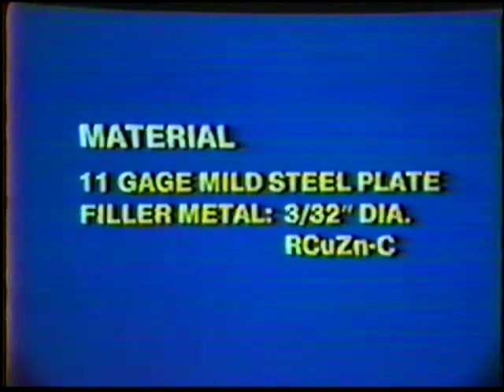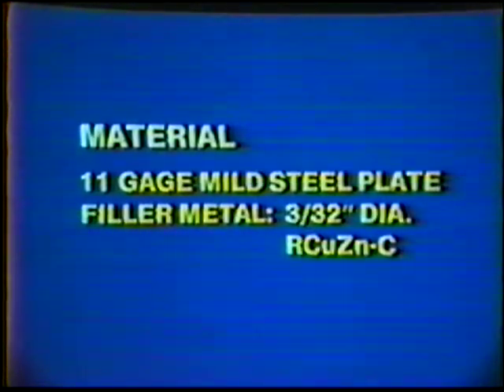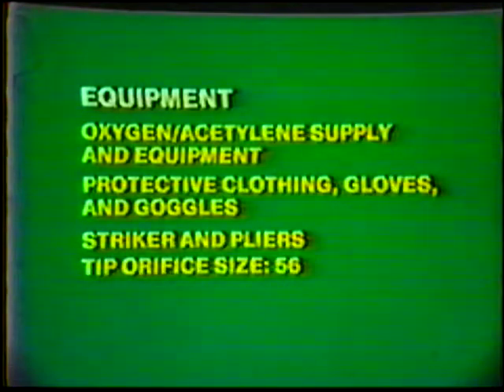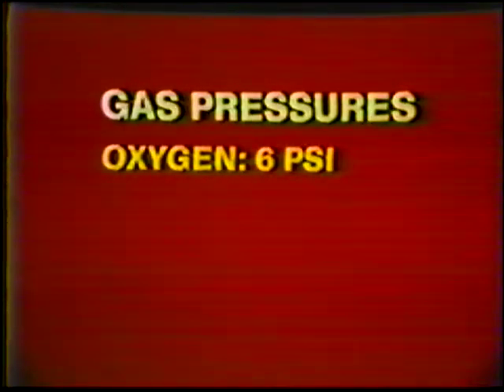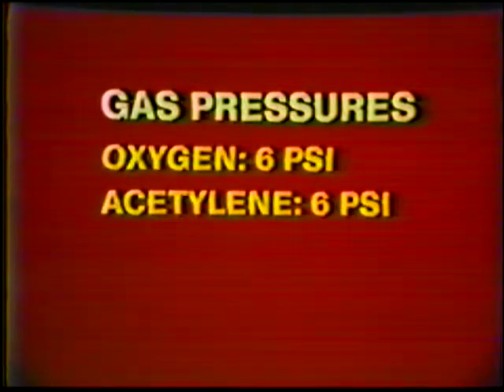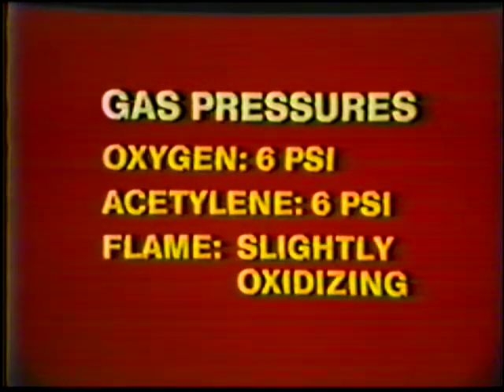Material: 11 gauge mild steel plate, filler metal, 3/32 inch diameter type RCu-ZnC. Equipment: oxygen and acetylene supply and equipment, protective clothing, gloves and goggles, striker and pliers, tip orifice size number 56, tip cleaner number 56. Gas pressure settings: oxygen 6 psi, acetylene 6 psi. Flame slightly oxidizing.